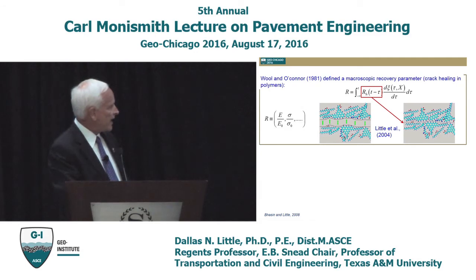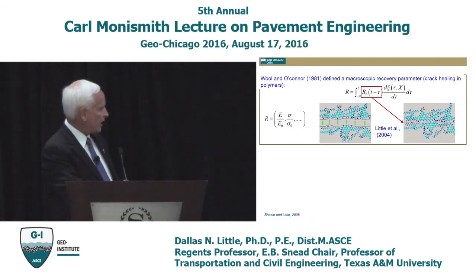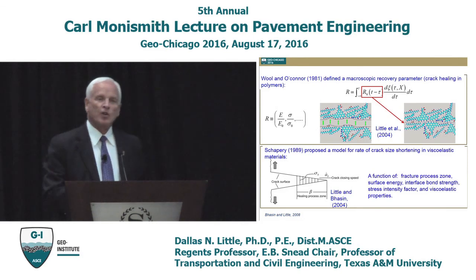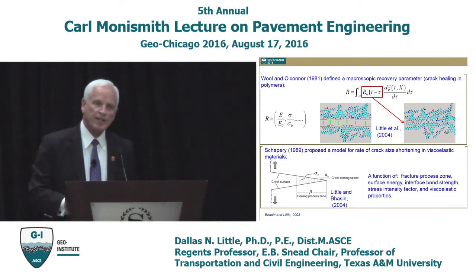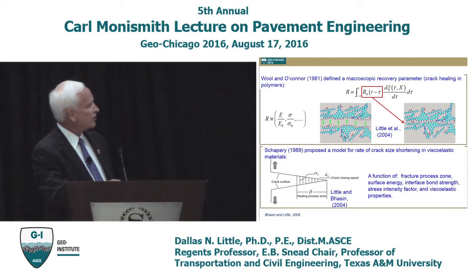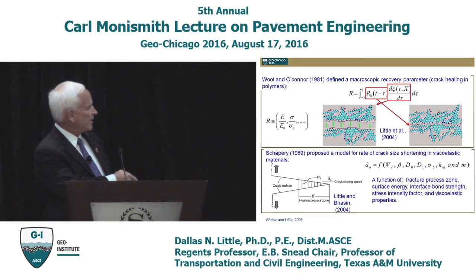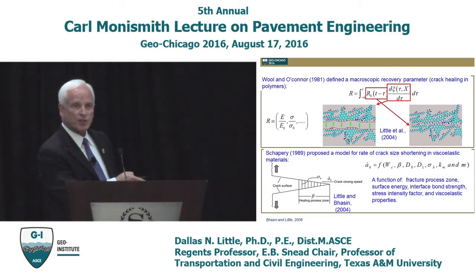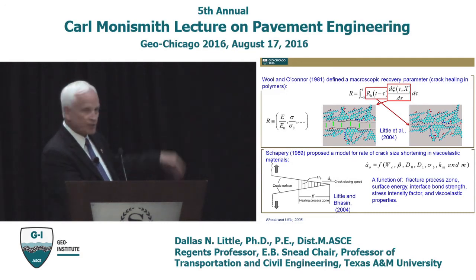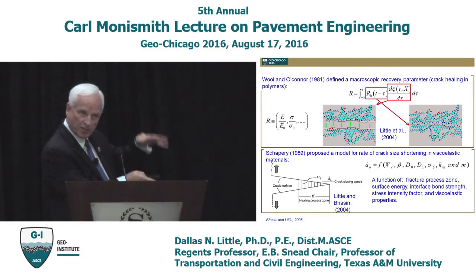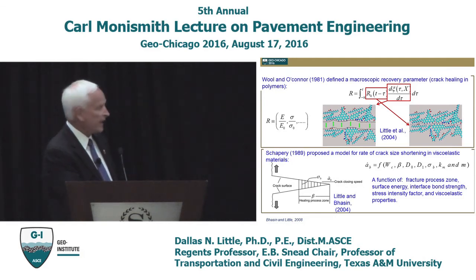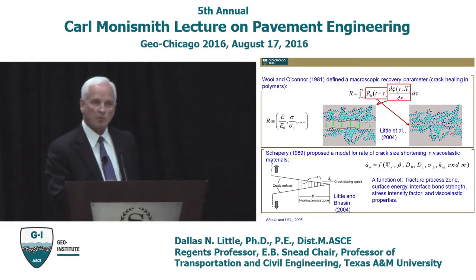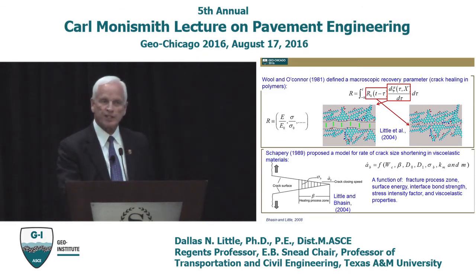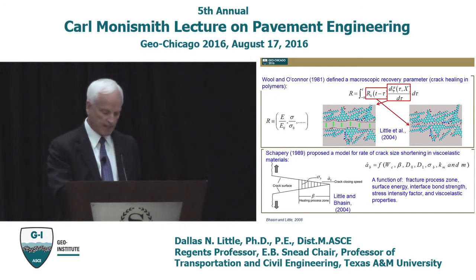And at about the same time, actually a little bit before that, Dick Schapery said, if you look at crack healing in a viscoelastic material, it's going to be a function of the size of the process zone, how big the crack is, the stress that will pull the crack back together, the viscoelastic compliance properties of the crack itself, how mobile is that crack to closing, how able is it to close, and surface free energy. So both claim that surface free energy has something to do with that wetting process and that healing process.